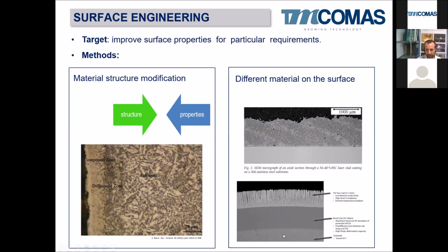Another example, in this case, is a thermal barrier coating. In this case, it is produced by the use of two different technologies. Here we can use, for example, a thermal spray coating of a nickel base alloy or MCrAlY, and then a top coat by, for example, PVD or electron beam, or thermal spray of, in this case, yttria stabilized zirconia. So this is a two-layer coating that will act as a thermal barrier to protect this Inconel substrate from the heat of the combustion chambers in some blades or some turbine components, for example. So basically, there are two ways to modify the surface: by modifying the top surface in the bulk material, or by using a coating of a very different material on top.